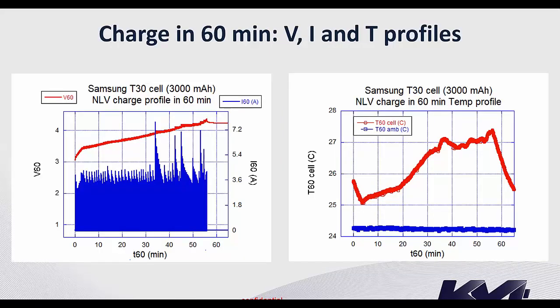So I will show you briefly the profile during charging of temperature, voltage, and current. On the left-hand side, the red curve shows the voltage during the charging in 60 minutes, and this is the current profile. So you can see the current is never constant, okay? And there are peaks of the current here and the others and so on. So this is a typical profile of NLV, and we were able to charge the battery here in 55 minutes, less than 1 hour. And this is the temperature profile in red. You can see that the temperature didn't exceed 28 degrees C. So 28 is here, okay? When the battery is kept in an environmental chamber at 25 degrees C or 24 degrees C.